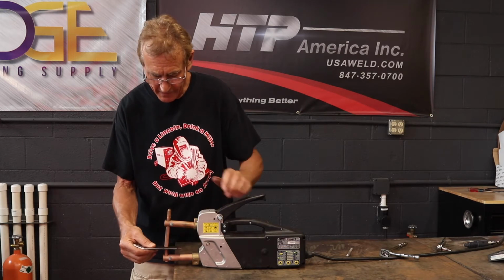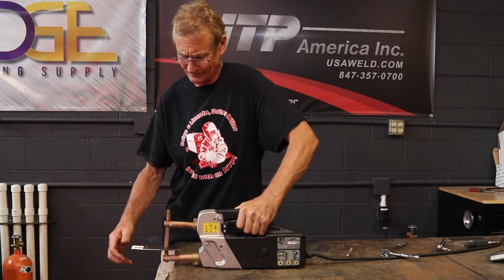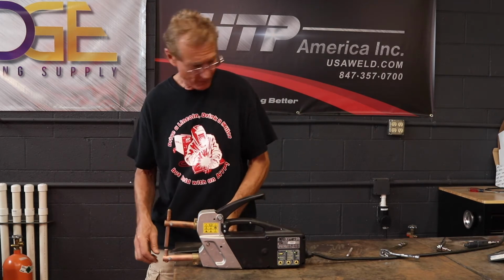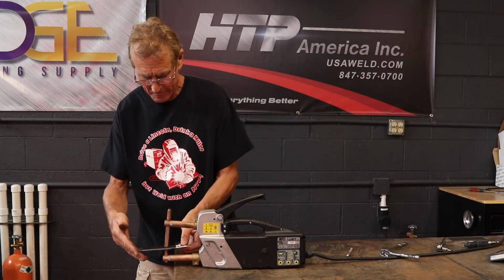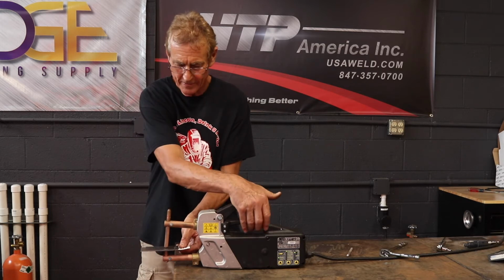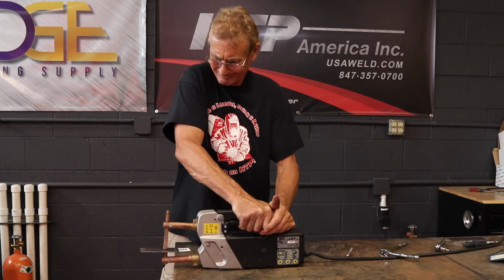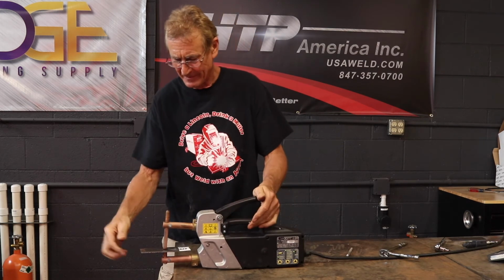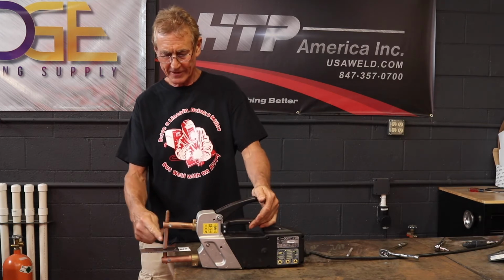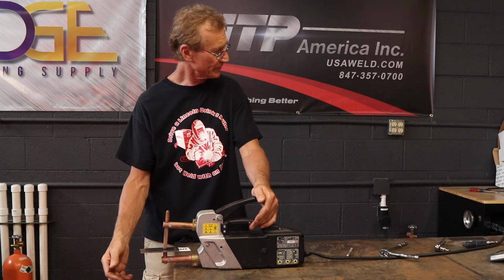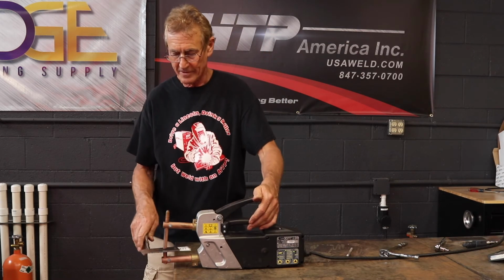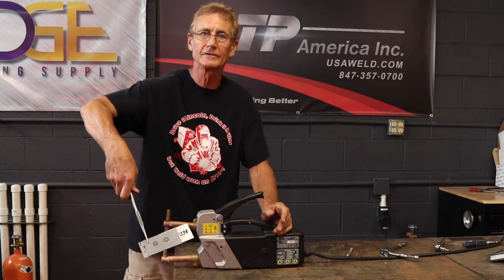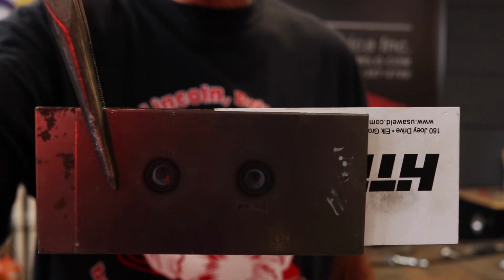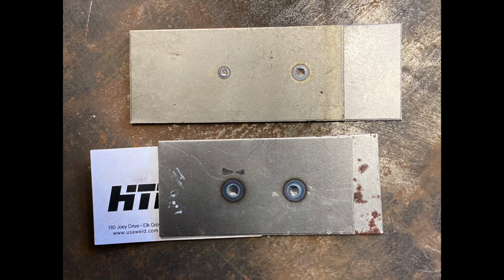So I will make a weld here. And now I will turn it around and make a weld in the area where the business card is. So what happened is the panels were connected electrically, and therefore it started to weld and burn through the business card. Now you can also see how much bigger the heat affected zone is. So now you can see how much larger the heat affected zone is with the setting up at the 2 plus 2 and in the pulse mode, but the pulse mode was necessary to burn through the business card.